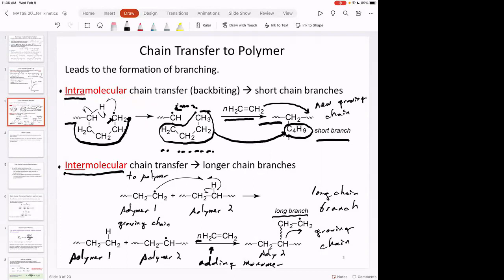It's very unlikely that you'll have 2 carbons in the short chain branch because it's really hard to get the polymer to backbite that severely. It's too much ring strain. And then it's also unlikely that you've got 10 carbons in that backbite. The conformation drives the 6-membered or 5-membered ring, not a 10 or 20-membered ring. That's a good answer.